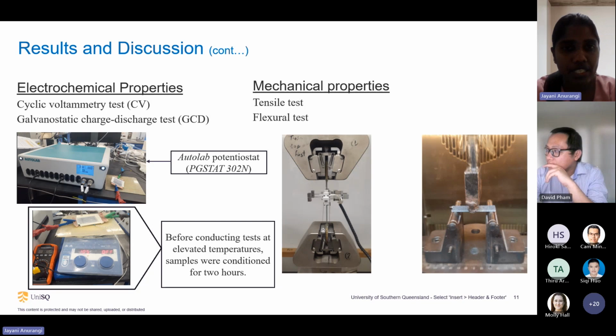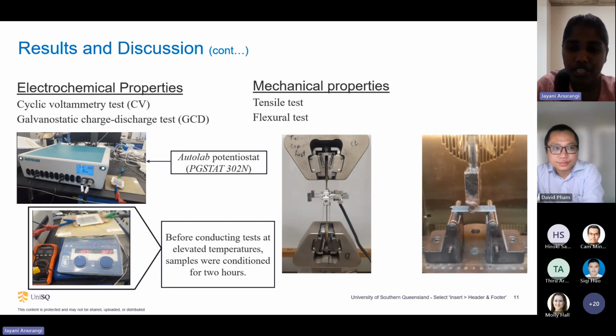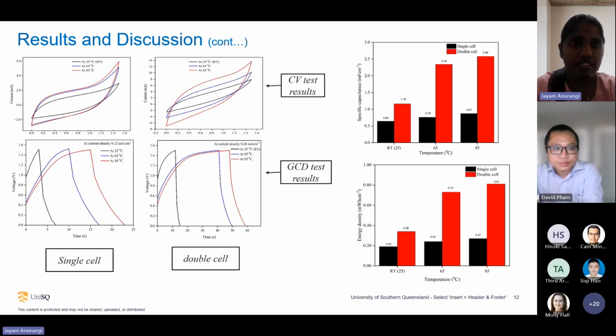When evaluating the properties at elevated temperatures, I conditioned the sample at the relevant temperature for 2 hours in an oven, and the measurements were taken while maintaining the corresponding temperature. This graph shows the electrochemical test results. The first 2 graphs are for CV test results, and the second 2 graphs show the GCD test results. These 2 graphs are for the single cell structural supercapacitor, and these 2 graphs are for the double cell structural supercapacitor.